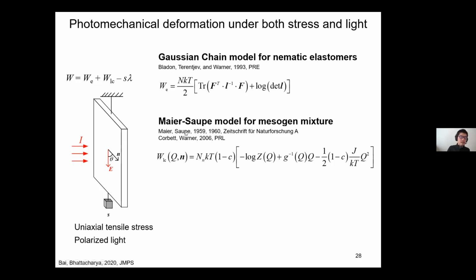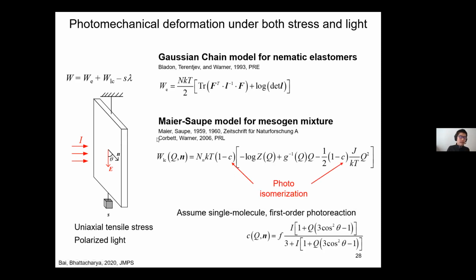And I can also have a microscopic model of this mesogen mixture. So this models the mesogen as a long-range interaction molecule mixture with dispersion force, very weak dipole-dipole-like dispersion force. So what Corbett and Warner did based on this model is they introduced this C parameter, which is the concentration of cis.